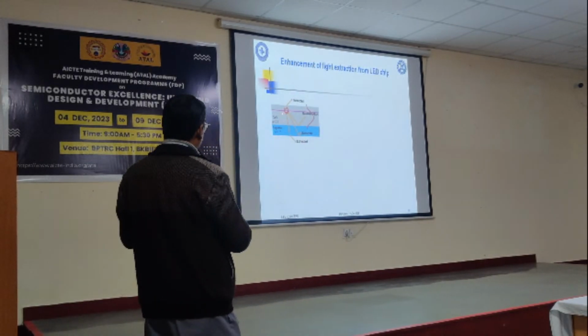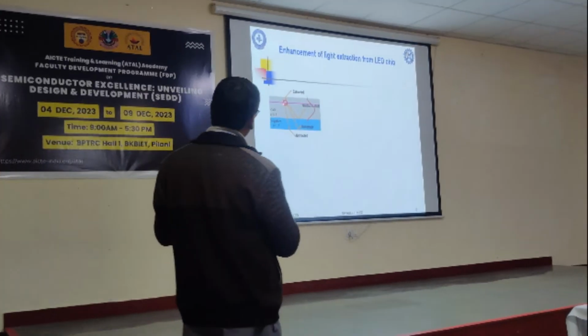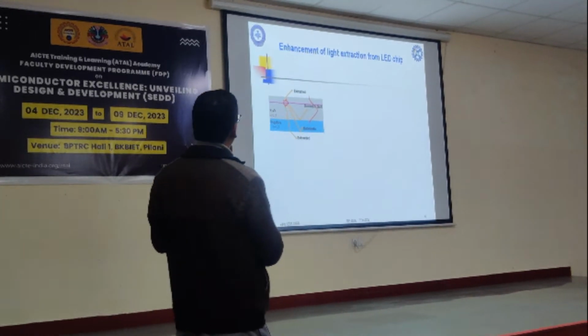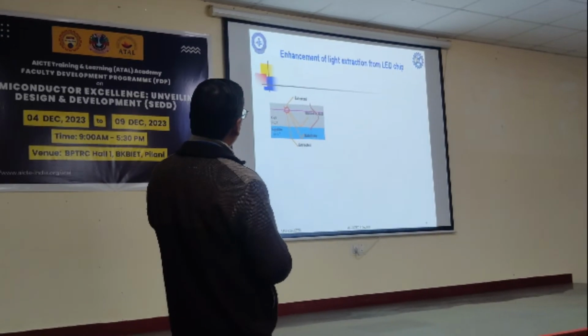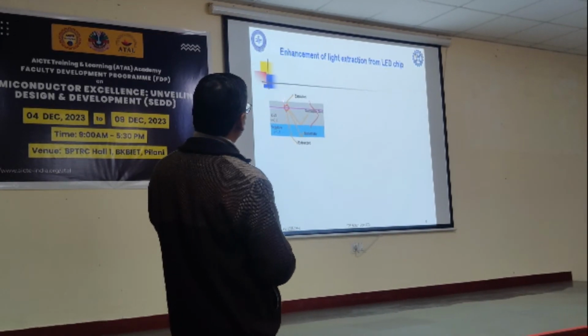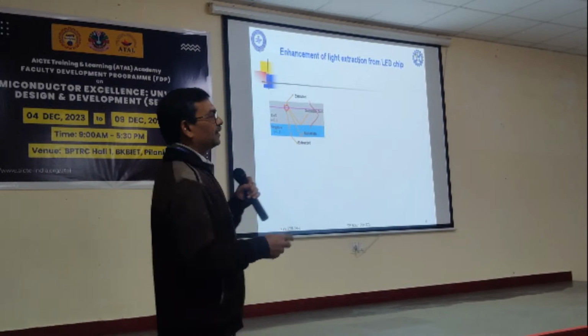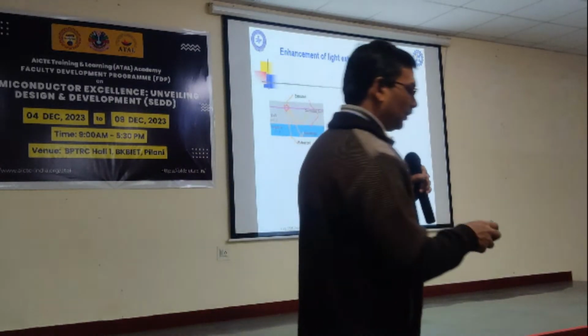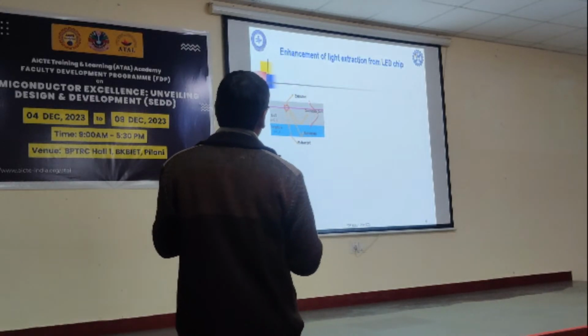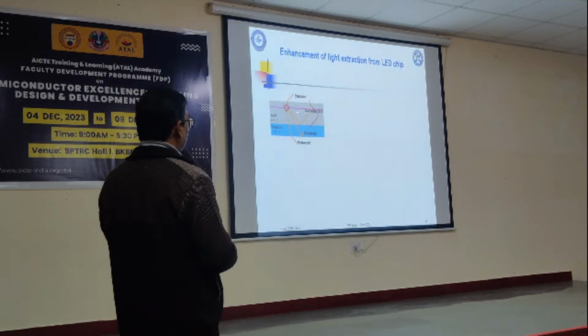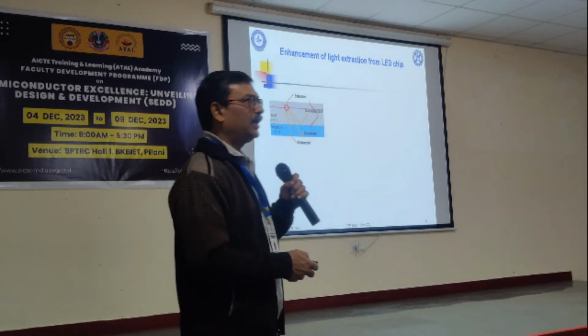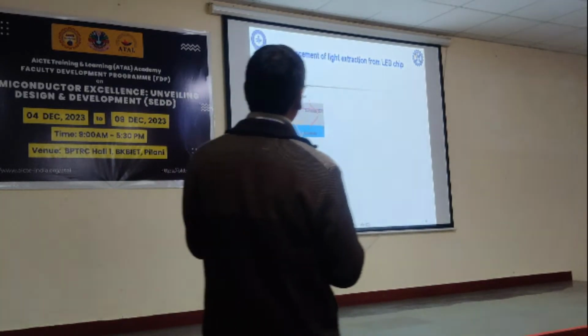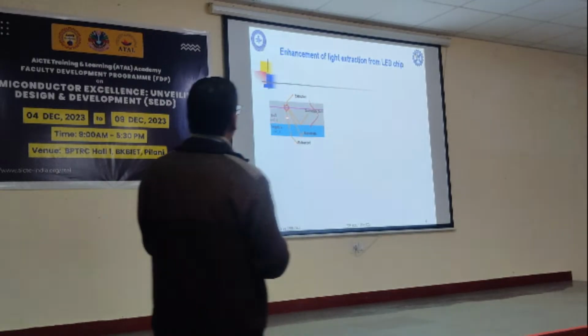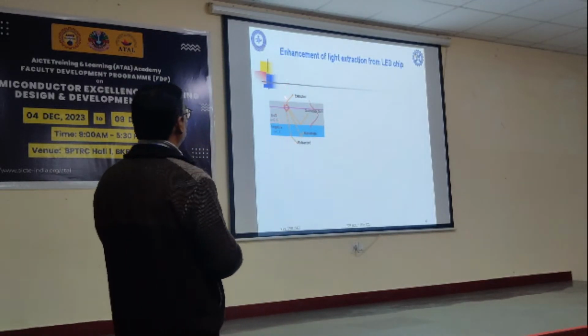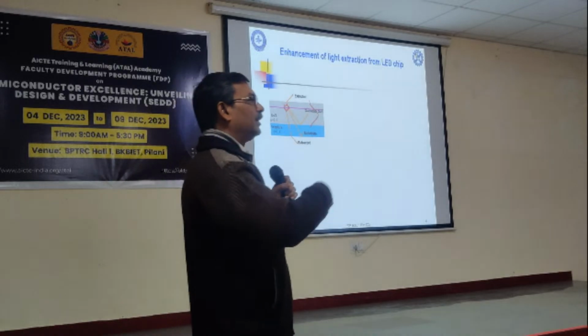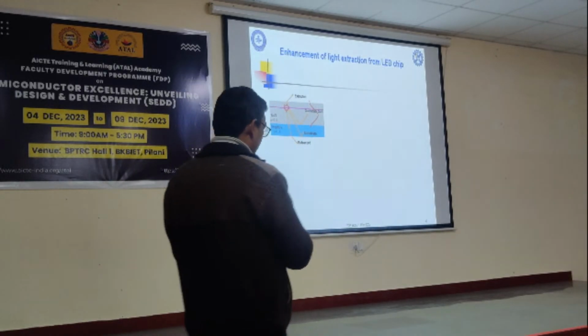So this is the region from where the light is being generated. One possibility is how to increase the escape cone, because the escape cone depends on the refractive index contrast, 2.5 and 1. If we incorporate a certain material whose refractive index is in between these two, 1 and 2.5, the escape cone will be increased to some extent.